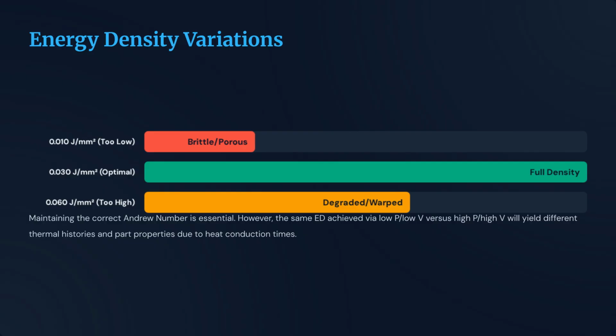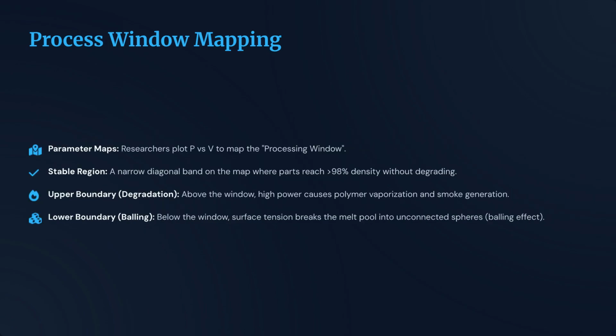While energy density is a useful metric, keep in mind that the same value can be achieved with different combinations of parameters. Different paths lead to different thermal histories, which can change the final mechanical properties of your part. Researchers create parameter maps to identify the optimal processing window. This is a stable region where parts achieve high density without degradation, bordered by risks like material vaporization at the top and balling effects at the bottom.